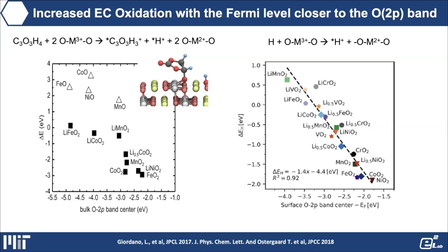This trend can be generalized by computing the adsorption strength of hydrogen on metal oxide surfaces. In collaboration with Jens Rossmeisel at the University of Copenhagen, we looked at hydrogen adsorption on various oxides plotted as a function of surface p-band center. Very similarly to what we see for dissociative adsorption of EC, as we go to more covalent oxide surfaces, the driving force to oxidize hydrogen, hydrocarbon molecules, or small organic molecules increases. We then sought experimental support for this framework.